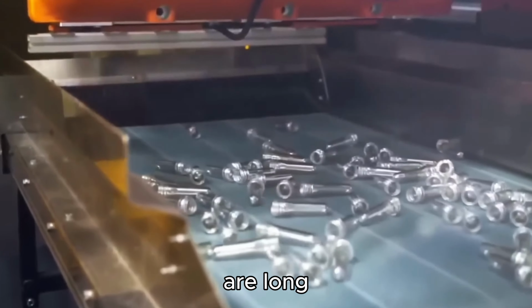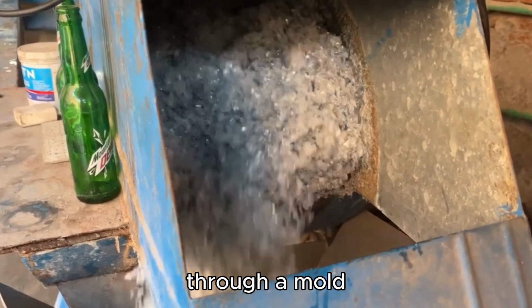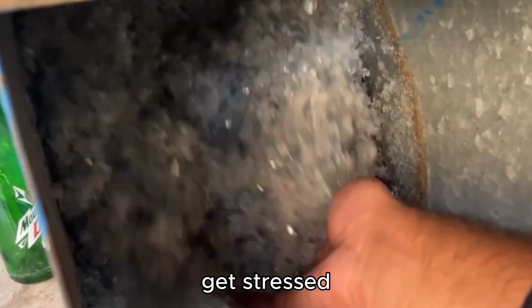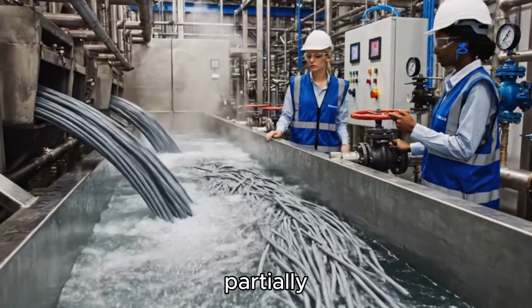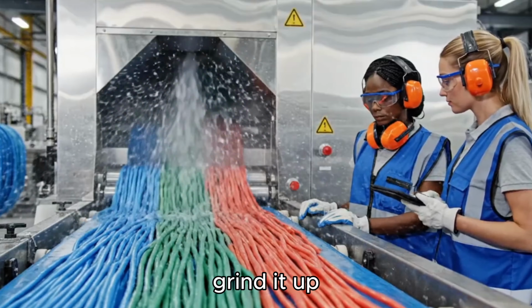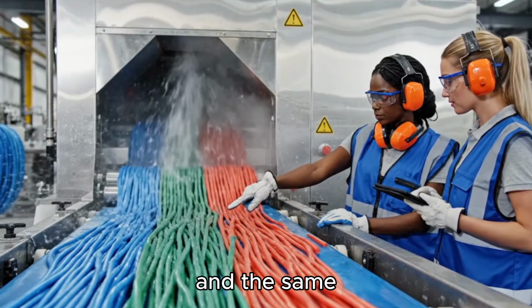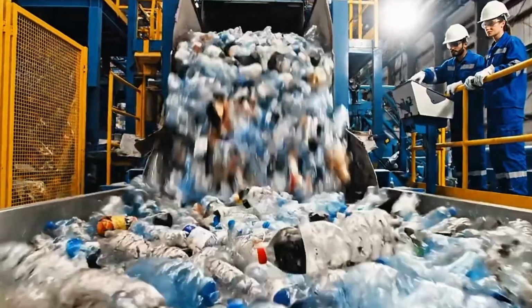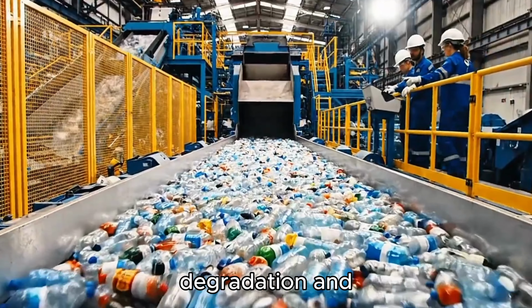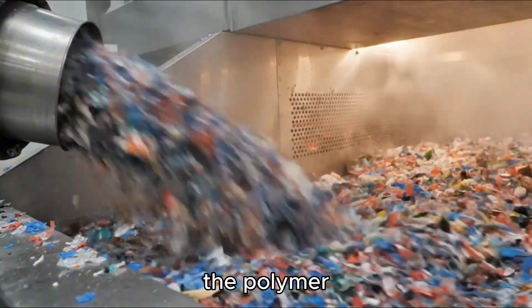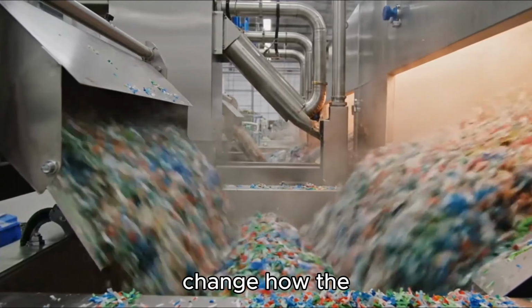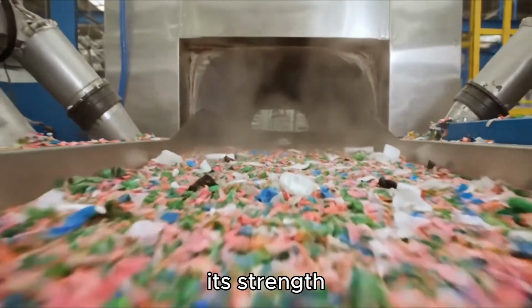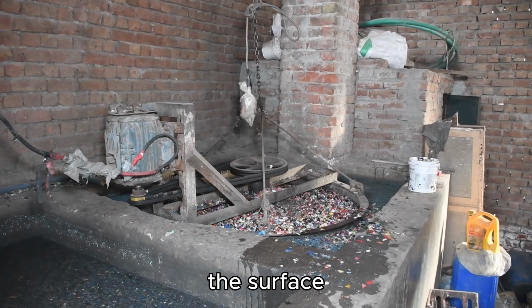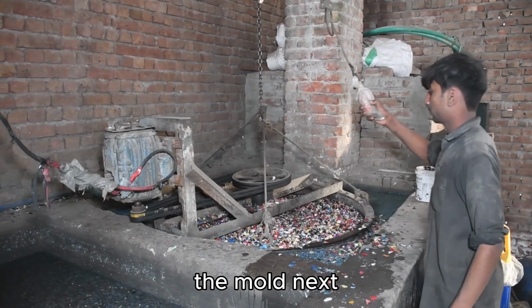Most plastics are long molecular chains, polymers. When you heat polypropylene or nylon or polycarbonate and push it through a mold under high pressure, those chains get stressed, they stretch, they shear, and they partially break down. Cool the part, grind it up, heat it again, and the same degradation happens a second time. Engineers call this thermal degradation, and with each heat cycle, the polymer chains get shorter. Shorter chains change how the material flows, reduce its strength in measurable ways, and can alter the surface finish of whatever comes out of the mold next.